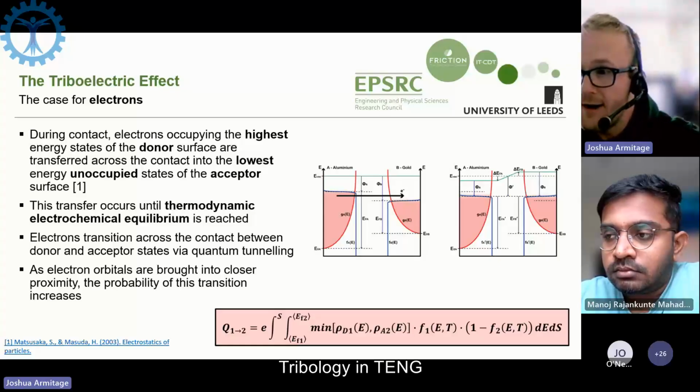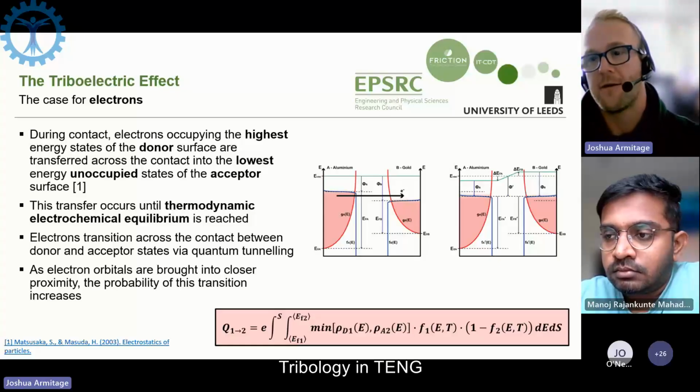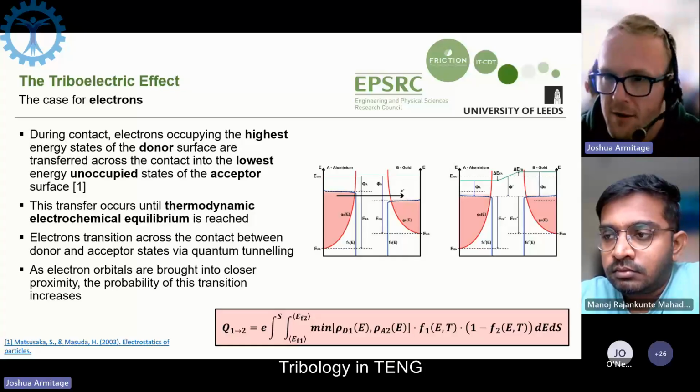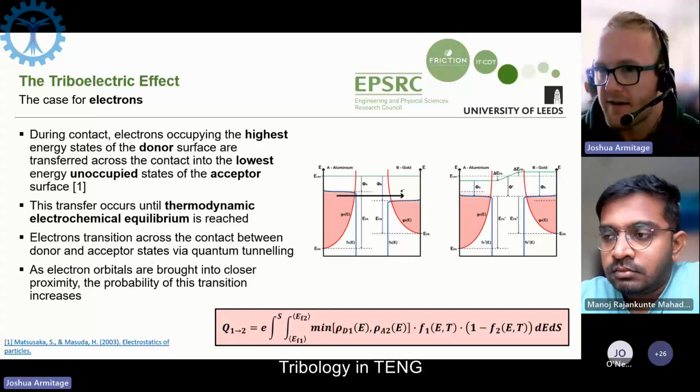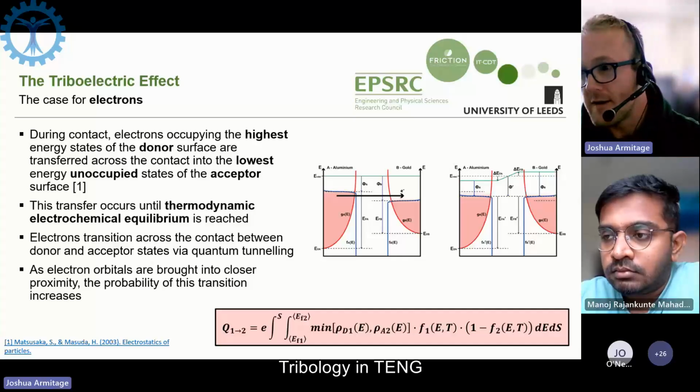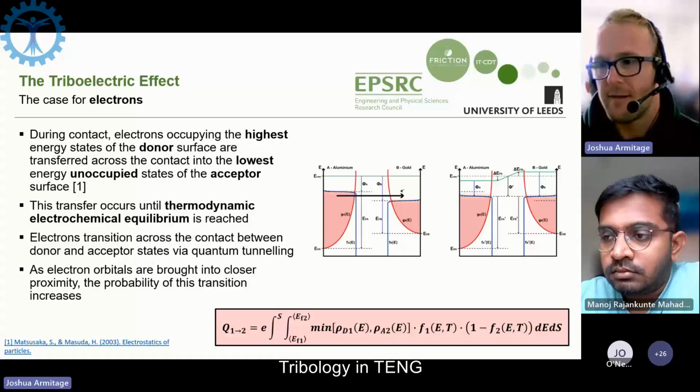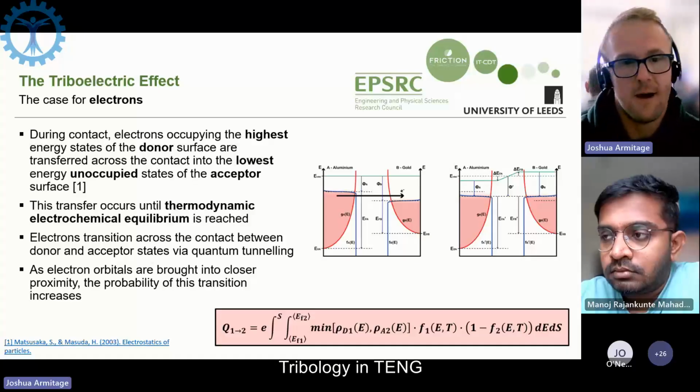So in this case, it's aluminium. It has a very low work function, therefore it's easy to remove electrons from it. And you can see that in terms of its physical properties. Aluminium is incredibly reactive. It readily creates a passive oxide layer when exposed to air. So it's something where the electrons are very easy to remove, and they're very easy to react with things. Conversely, you have gold, which has a relatively high work function. It's difficult to remove electrons from that material. Therefore, it doesn't really react with anything, and it's known as a noble metal.